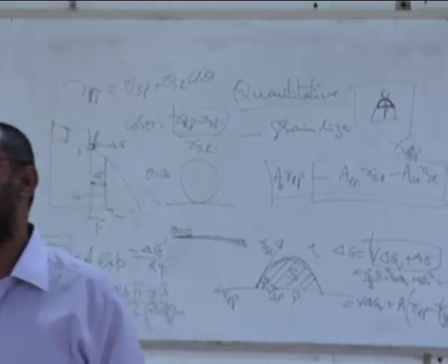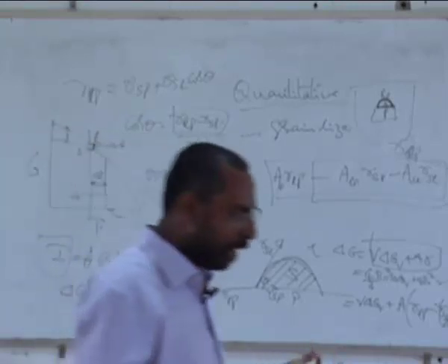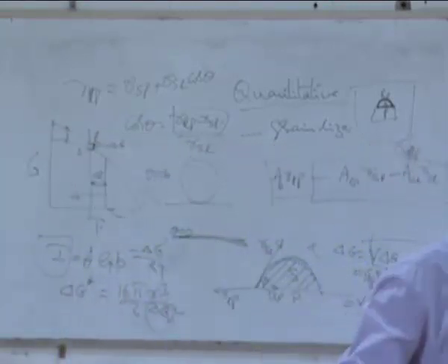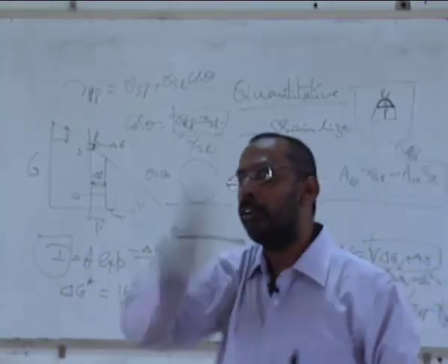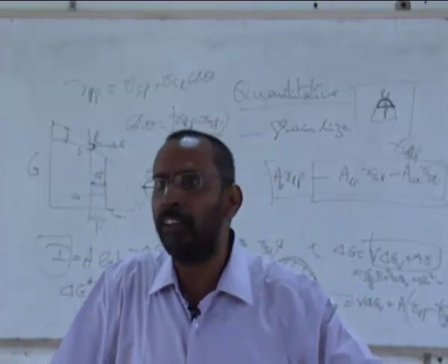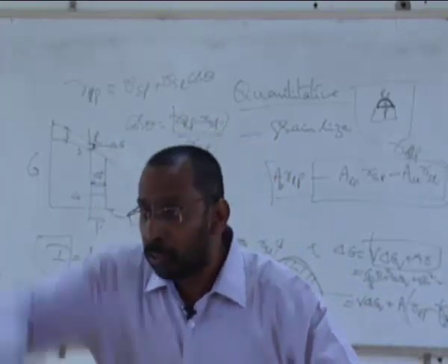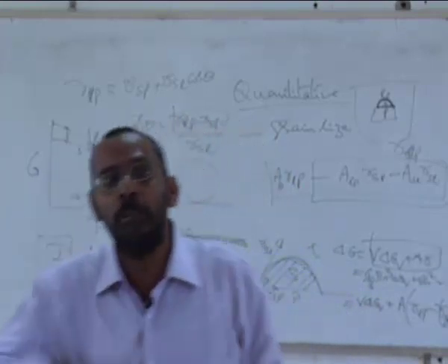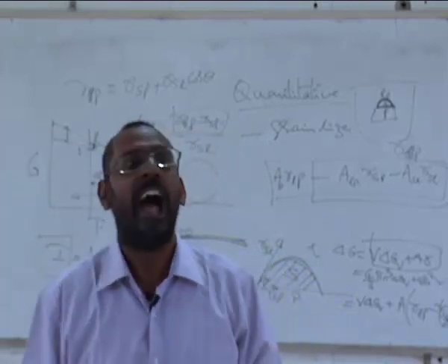Otherwise, it will not. That's why I cannot take a liquid of, let's say, aluminum and simply take some sand particles, drop them into liquid aluminum, and expect them to work as nucleating sites. They will not work. I need to add those particles which have similar crystal structure as that of the solid that is nucleating.